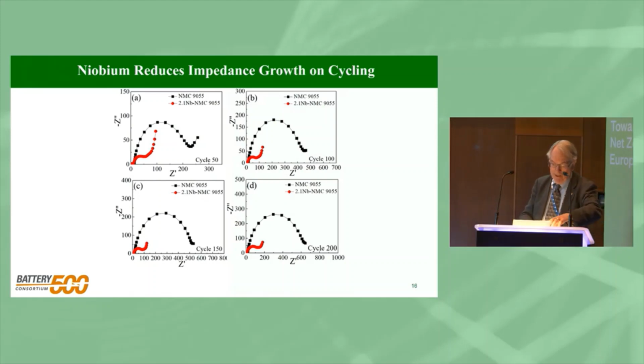And the reason it's stabilizing the lattice, it's stopping the formation of these resistive films on the surface. So the black here is the pure material. Here's the one with 2%. So you can see in cycle 50 here, here's the black one. Resistance has increased, much less on this one. Now here's the 150th, 200 cycle, always increasing for the niobium-free material. The resistance is much, much lower for the niobium-treated material. So we've eliminated, for practical purposes, that resistive layer on the surface.